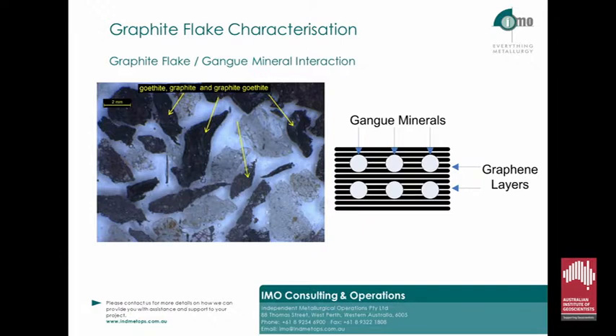Most of you will be aware that a graphite particle is made up of graphene layers stacked on top of each other, and that graphene is defined as a single layer of graphite. If there is gangue between the graphene layers within a graphite particle, then liberating that particle is the only way to liberate the gangue from the graphite particle, as the caustic and acids won't be able to diffuse through the graphene layers to remove the gangue within those graphite particles.